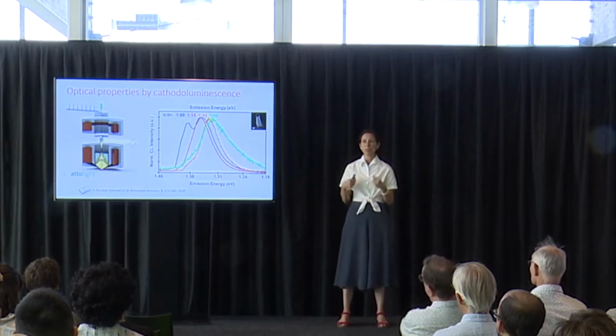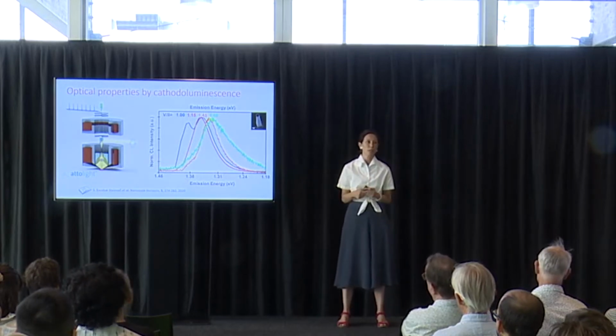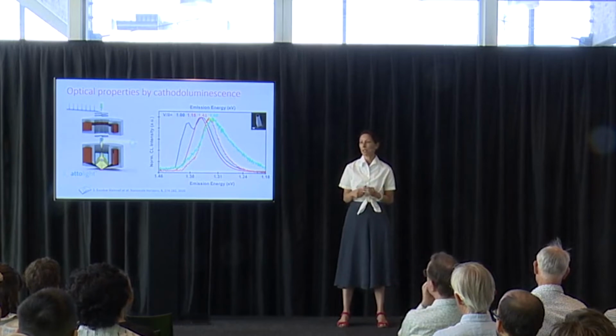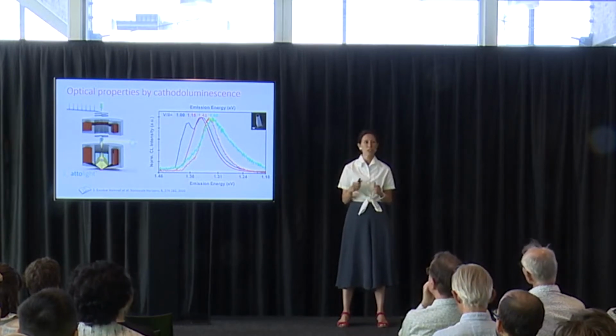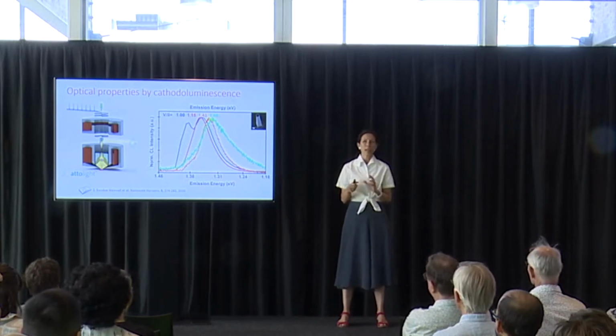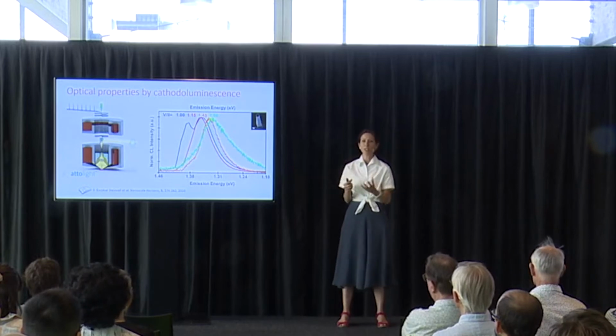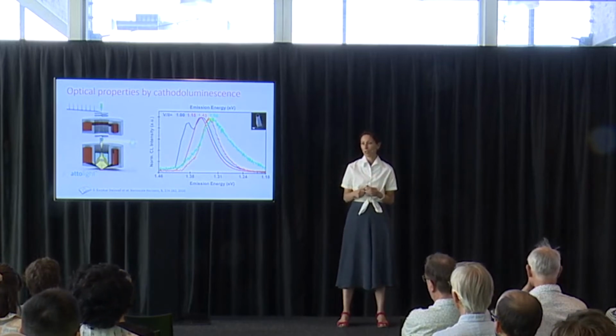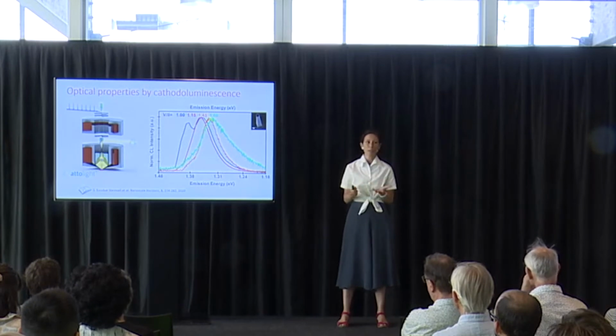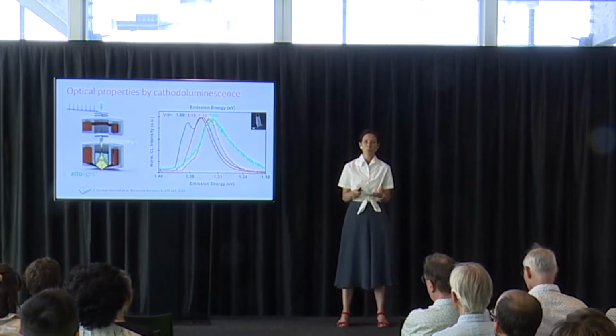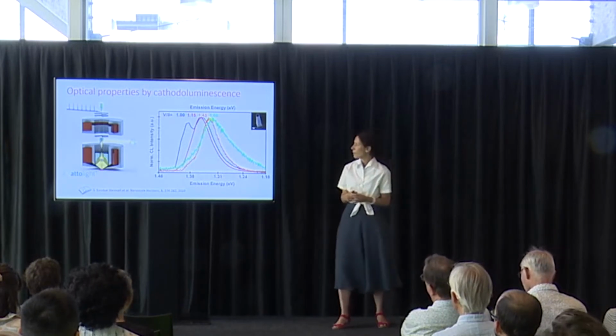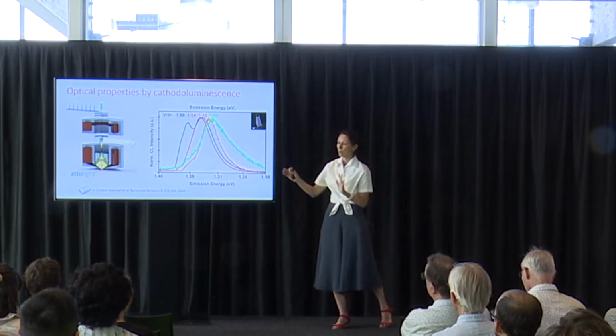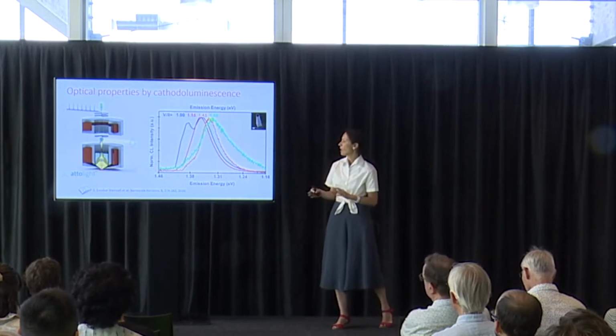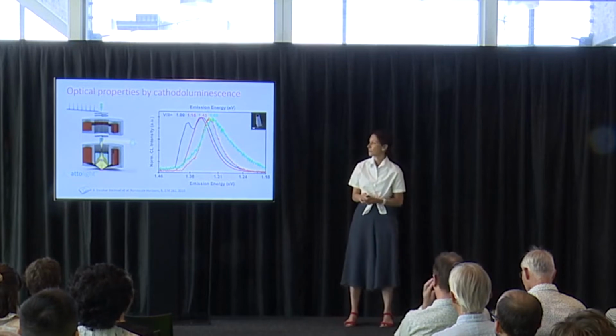So it looks like it's a compound semiconductor, but quite interesting. It's probably that one of the elements, probably the phosphorus, changes the oxidation state, and this allows you to have a material that still doesn't have these deep recombination centers. This is something that we still want to study, and this is one of the questions we still have to understand about the material. But as you see, we change the band gap or the emission position, and this can also be useful for applications.